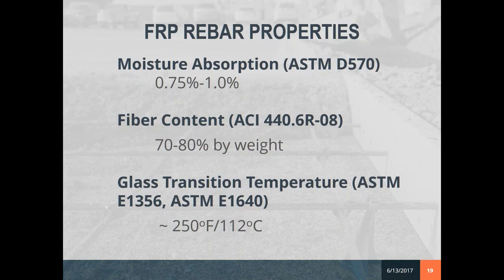So generally, with these type of products, when you're writing specs or looking at specs and codes, you want that moisture absorption to be between about 0.75 and 1%. When the glass industry first started, they had some issues with the moisture absorption with the concrete, also some alkalinity. The fiberglass industry has developed different levels of the fiberglass, the E-glass and S-glass, and have addressed these issues in order to meet these standards and specifications. The fiber count, again, by requirements is generally between 70 to 80% fiber, and the remaining portion is the epoxy that's holding that together.